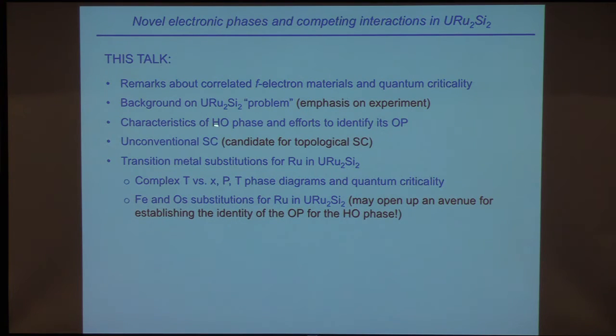Talk a little bit about the characteristics of the hidden order phase and efforts to identify its order parameter. It exhibits unconventional superconductivity, is regarded as a candidate for topological superconductivity. And then I want to concentrate on the transition metal substitutions for ruthenium in this compound. Again, you get these complex phase diagrams and quantum criticality. But in particular, if you substitute iron and osmium, it appears to open up an avenue which may allow one to hopefully identify the order parameter for this hidden order phase.